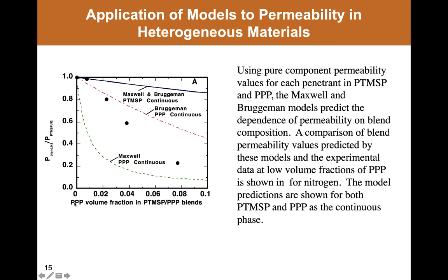And what you can see is that at very low volume fraction, the permeability properties for this first point follow the Maxwell and Bruggeman models. They give essentially the same prediction at this low volume fraction, when PTMSP is taken to be the continuous phase. And shortly thereafter, at somewhat higher volume fraction of polyphenyl propyne, you start to see a marked deviation from the Maxwell and Bruggeman model where PTMSP is presumed to be continuous.